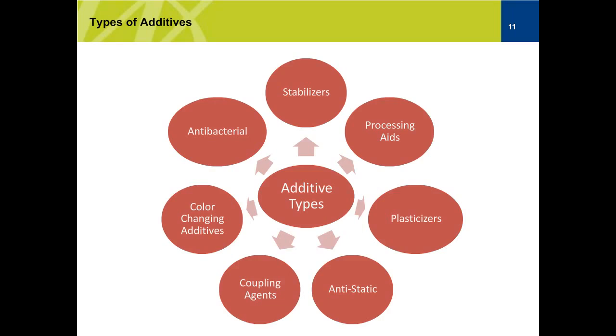We've seen leaching, but we also have plasticizers, which are basically additives to increase the plasticity or flexibility of the plastic material. We have anti-statics, which are additives that allow the polymeric material to disperse static electricity charges. We have coupling agents, and this is just to increase the interaction between polymer and filler if the company is using a filler. Color changing additives or pigment.